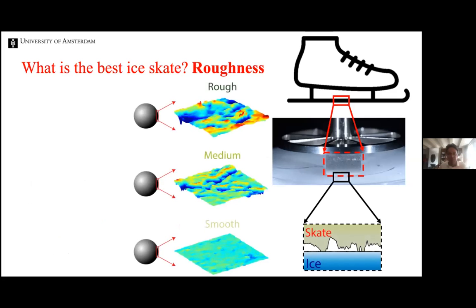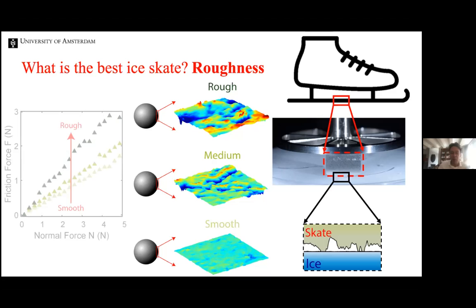The other thing that one could worry about is the roughness of the skate. Should it be rough? Should it be very smooth? You could argue that if your skate is rough, there's only a small contact area between your skate and the ice. And so the smaller the contact area, perhaps the smaller the friction coefficient, because you have to displace fewer of these molecules. We can do different roughnesses. This is again a sphere. We can make the spheres rough, and we see, as you would intuitively expect, that the smoother the skate, the lower the friction force. And that's very interesting.